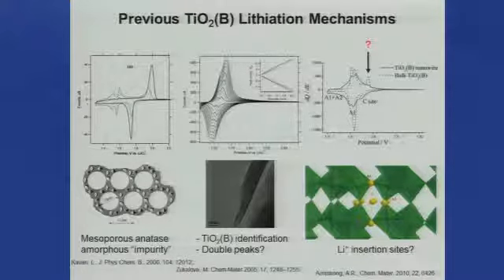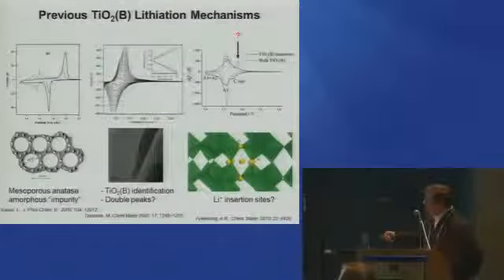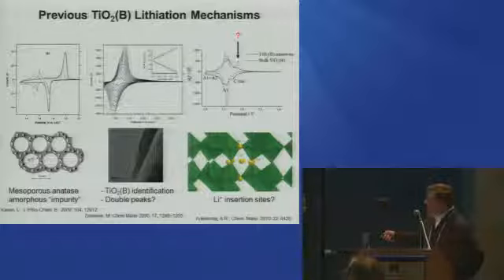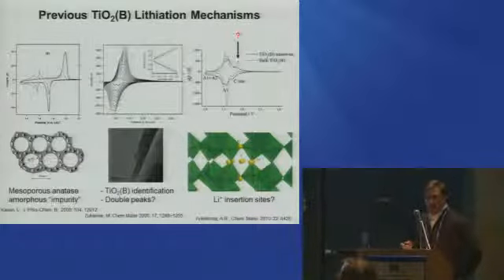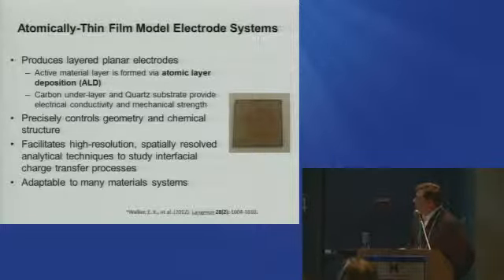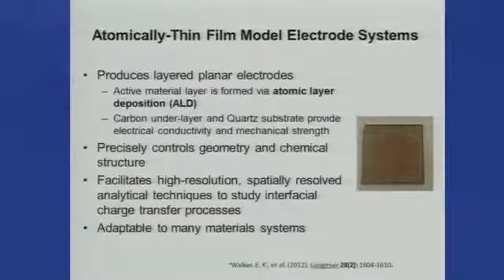And so this labeling of the C site in TiO2B nanowires is really not the case, because this is the anatase peak. And it's these other 2 peaks that are related to the geometry of this nanowire that are still very surface-oriented in terms of how they lithiate. Of course, we don't really have a good spectroscopic handle, and we wanted to get more sensitive in terms of what type of chemistry is going on when we lithiate and delithiate these materials.